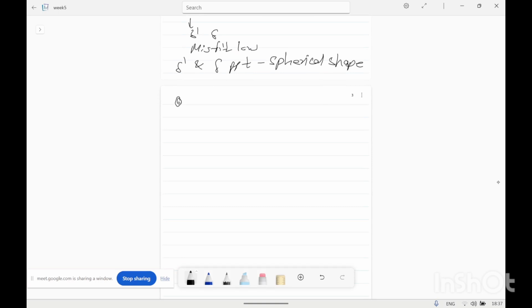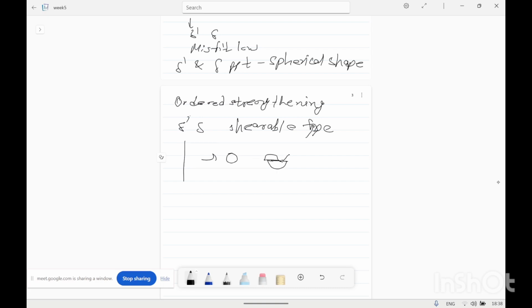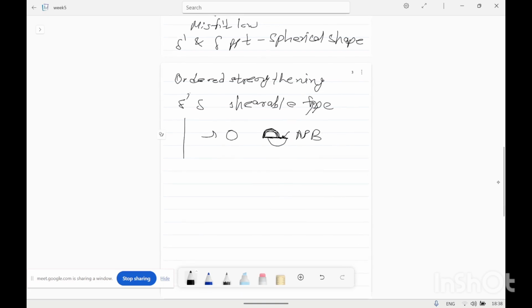So how does order strengthening happen in the 8000 series alloy? The delta prime and delta precipitates are shearable type. This means as the dislocation moves through the precipitate, it shears it and forms an extra surface, that is the antiphase boundary. The formation of the antiphase boundary increases the applied stress required for further deformation to continue, and thereby increases the strength of the alloy.